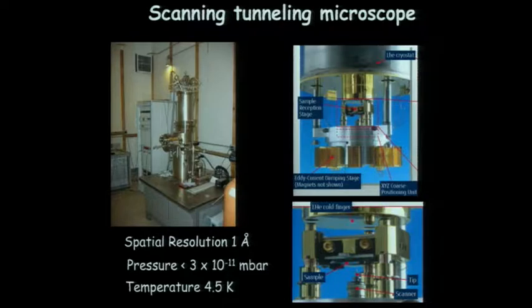The sample is fixed, and then the tip is scanning, and we're doing our measurements at low temperature with ultra-high vacuum to try to keep everything nice and clean inside.